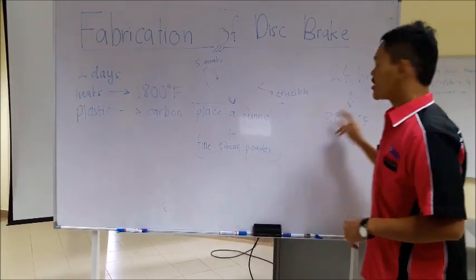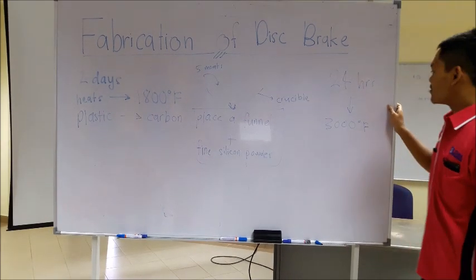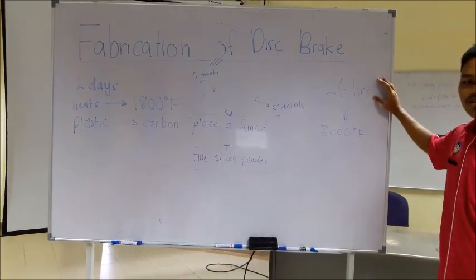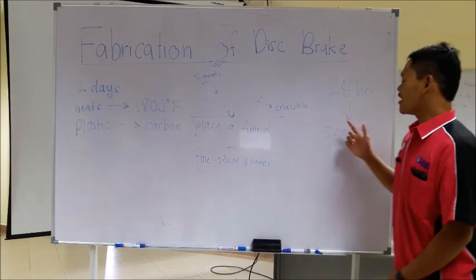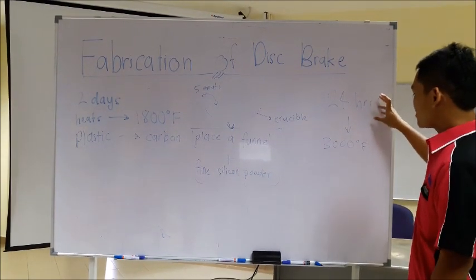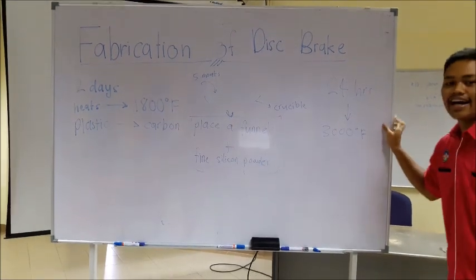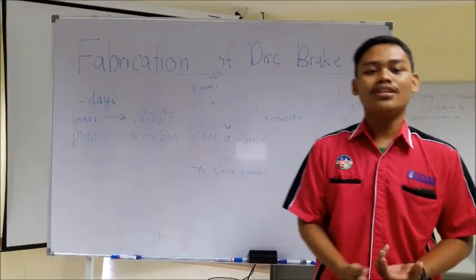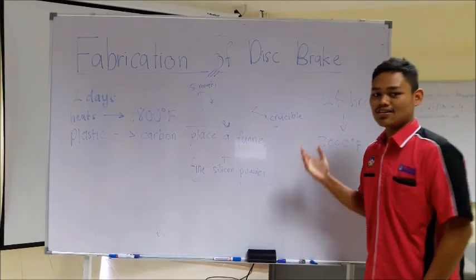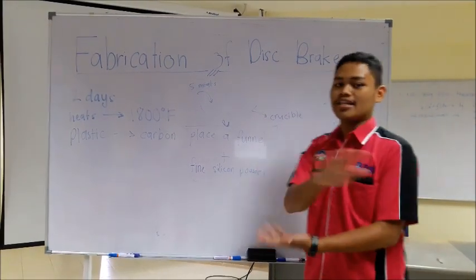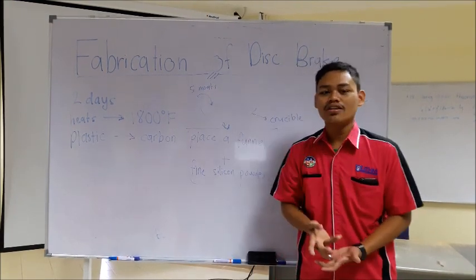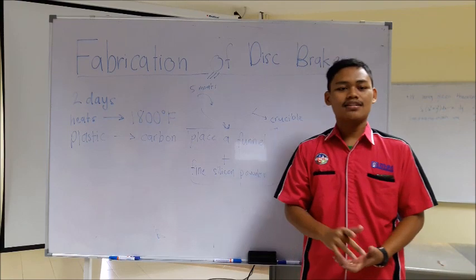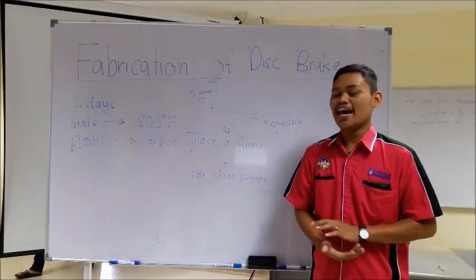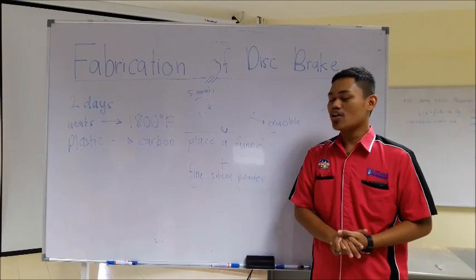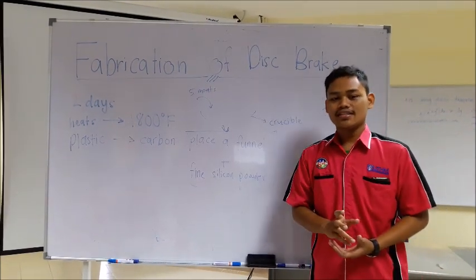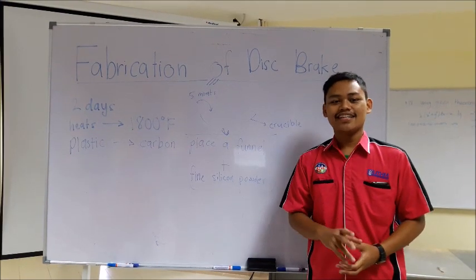Then load the crucible into a furnace for 5 minutes at 1,800 degrees Fahrenheit, and then heat the disc ring until the silicon powder is melted completely, and the liquid silicon drowns into the disc ring. By this process, the disc ring forms a completely new material called silicon carbide, which makes the disc ring exceptionally hard.